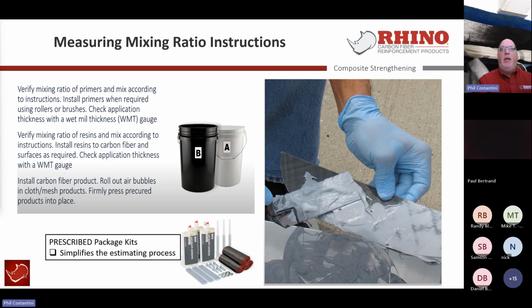Your mixing ratio, your consistency has to be there when you're applying it onto the structure. To simplify it on smaller jobs, the cartridge sets work very well. This is a classic example of a cartridge set kit for a bowed wall where you have 3 strips needed, whether they're 7 foot, 8 foot, or 10 foot, the static nozzles that mix and blend the materials, and then the anchoring bolt system that comes for your sill plate connections. This is a classic example of the Rhino carbon fiber bowed wall kit, but on larger projects, if you're doing a bridge girder, an underground parking garage, or a repair somewhere in a more commercial environment, the bulk packaging of the 5-gallon pails is a lot nicer way to deal with larger scale projects.